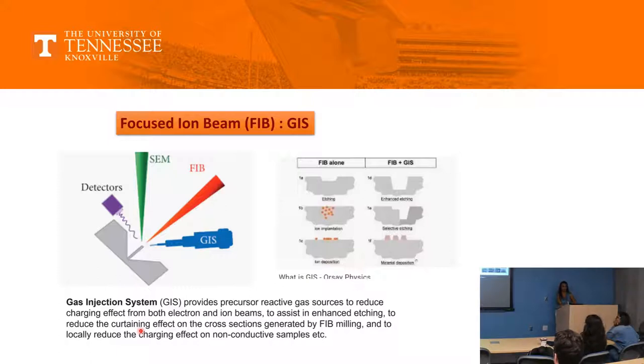Now, in the focused ion beam, this is your sample stage. If you make the stage absolutely parallel to the ground, you will be absolutely perpendicular to the SEM, and you would be able to have a clear view. As soon as you want to do FIB, you tilt the sample holder towards the FIB gun. This is the gun that will be used to sputter your sample. As I explained last time, from a very thick sample, we are going to a 100 nanometer layer. And then the third thing that we have is GIS.